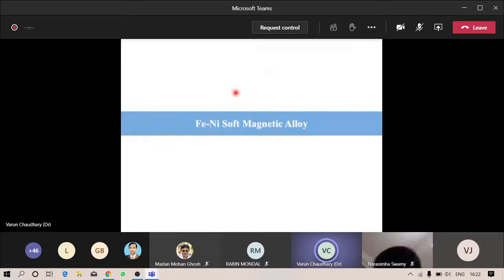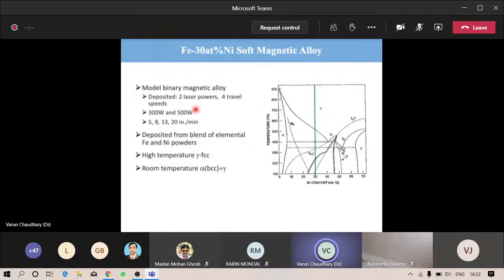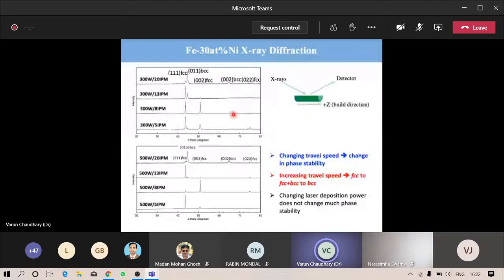So before moving to the graded samples, we started with the model iron nickel soft magnetic material, which is commercially available, using different process parameters to see the effect of process parameters on the final product. Here is the phase diagram, and this particular composition has gamma phase at high temperature and alpha plus gamma phase at lower, room temperature. These are the results, the X-ray diffraction patterns for all the samples prepared with all these process parameters. And we found that when the travel speed is low, the sample shows a face-centered cubic structure, which is converted to a BCC-dominated structure when we increase the travel speed.